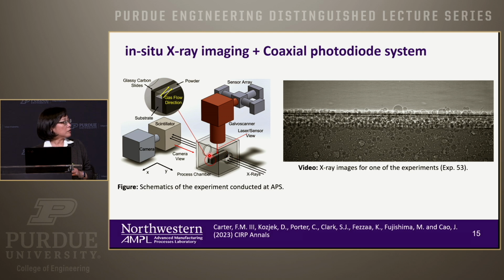And here, one thing is because of the power of the X-ray, for material-wise, it's about 400 micron thick, okay? Therefore, it's really localized. But we can learn a lot from this. And the idea of this is that I want to have the ground truth, and then we have this sensor array, which is a photodiode system.